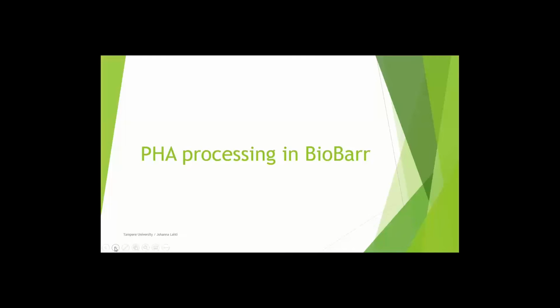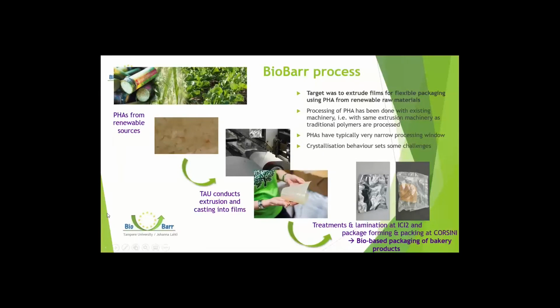Then we move to the actual topic of how we processed PHAs in this project and which grades we used. So this slide shows the BioBarr process. Our target was to extrude films for flexible packaging using PHAs from renewable raw materials. We did the processing with existing machinery, so the same extrusion machinery as we use for processing traditional polymers. We had to tackle the typical narrow processing window of PHA in extrusion, and also the crystallization behavior, as I mentioned before, set some challenges. So we are using PHAs from renewable sources.